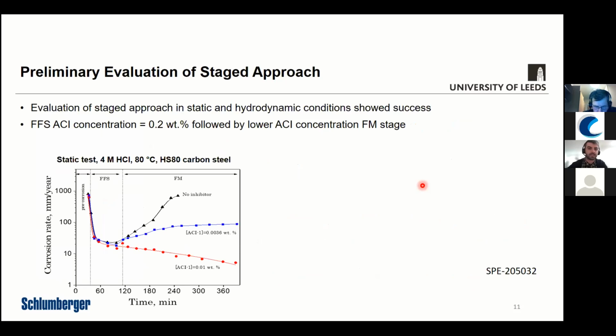So just to give some of their results. What they found when we completed static tests in 4 molar hydrochloric acid at 80 degrees C with HS80 carbon steel was that the film forming stage dramatically reduced the corrosion rates.